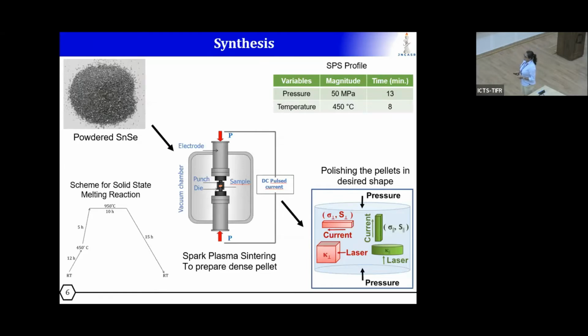Coming to the synthesis part, these samples are synthesized by a solid state melting reaction, by melting the starting materials at 950 degrees centigrade. The ingots are crushed to powders, and the powder samples are sintered to prepare dense pellets at 450 degrees centigrade and 50 megapascal pressure. As I have mentioned earlier, SnSe shows anisotropic properties. So the pellets have been cut and polished into different desired shapes to measure the thermoelectric properties.